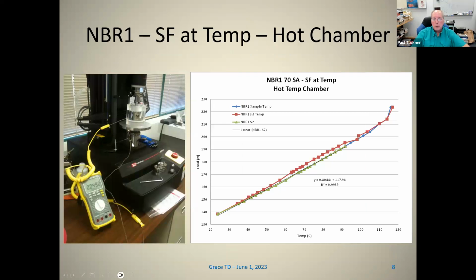Here's another picture of the high temperature chamber, where you would take a jig out of the oven, place it in the quartz chamber, insert a thermocouple into the CSR jig, put the indenter pin in, and run the CSR test like you normally would at room temperature. But as you monitor the temperature while the jig cools, you can do load deflection curves and determine what the sealing force is, and see how it changes as a function of time.